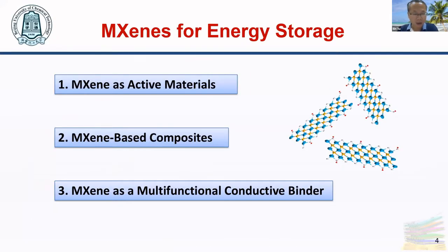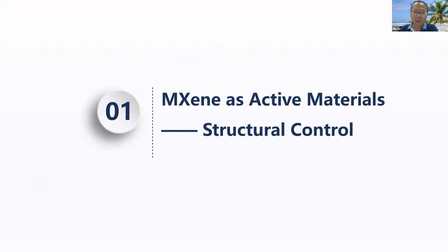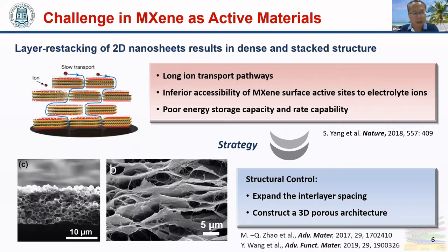This is my outline. I will talk about our recent work on MXene for energy storage in the following three aspects. The first part is about MXene as active materials. In this part, most of our work focuses on structural control of MXenes. MXenes can be used as active materials for supercapacitors and batteries. However, the layered restacking of 2D nanosheets results in a dense and stacked structure of MXenes. This will lead to long ion transport pathways and inferior accessibility of the MXene surface to the electrolyte, thus limiting the energy storage capacity and rate performance.